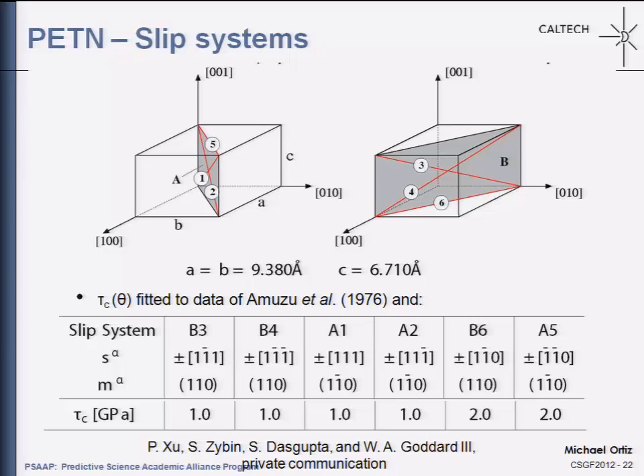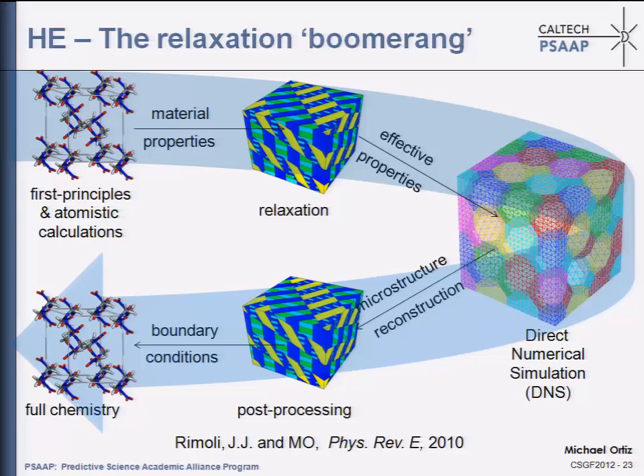So we're saying there is very little that is known about these molecular crystals, for instance, PETN. So what are the active slip systems? What are the yield stresses for the activation of plasticity? Those are, for the most part, unknown, or were computed from quantum mechanical simulations. And at that point, we are in a position where we have a baseline model at this level. We can unleash the microstructural calculations and then compute effective behavior and use it at this level.